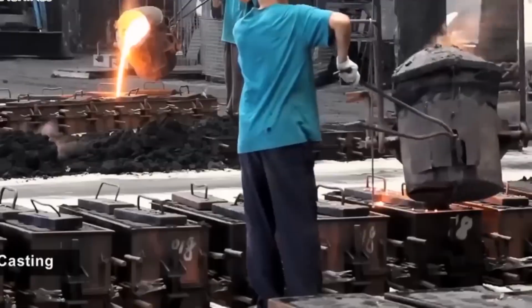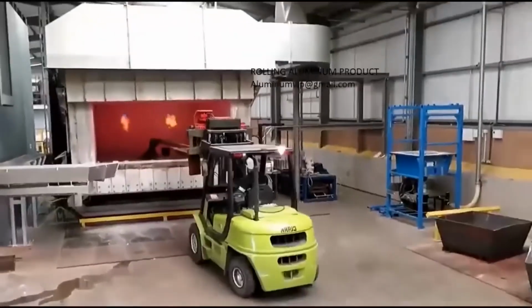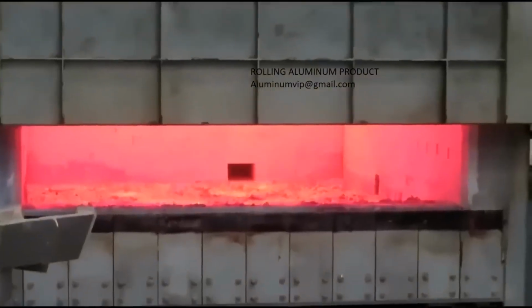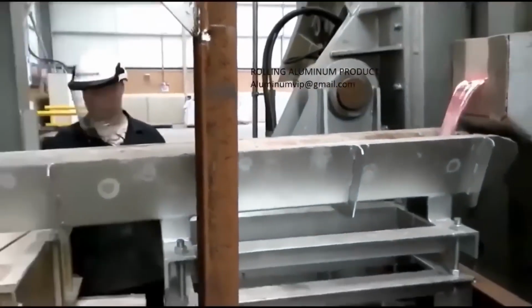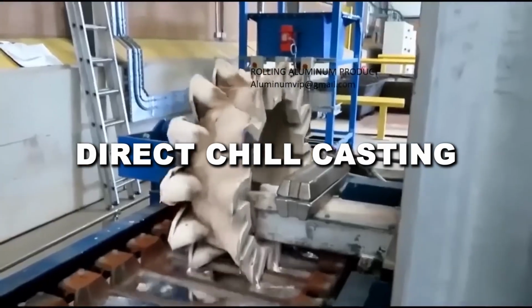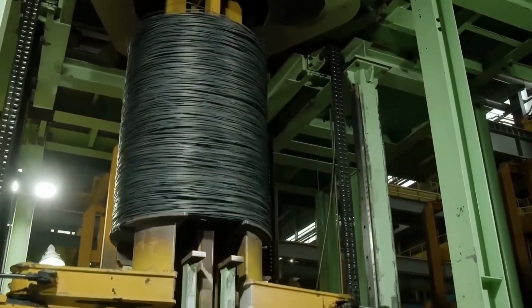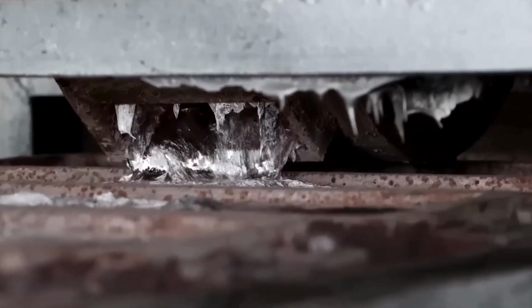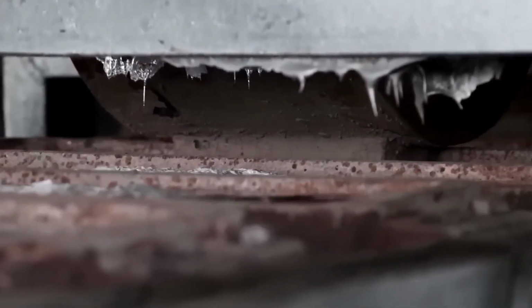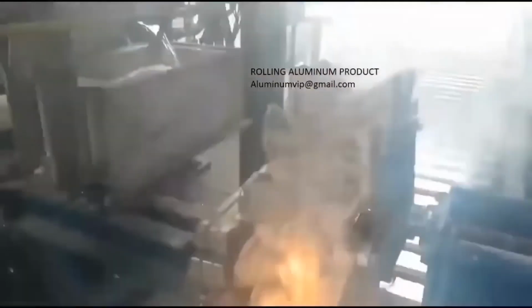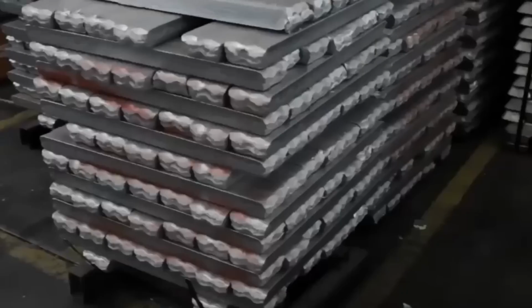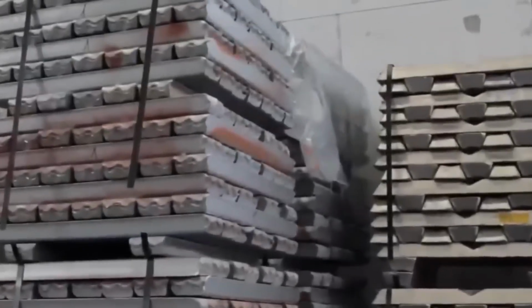The molten aluminum is carefully poured into massive molds where it begins to take on a solid shape. One of the most common methods used in aluminum recycling is direct chill casting. This technique involves continuously pouring molten aluminum into a mold while spraying it with water to rapidly cool the surface. The sudden temperature drop prevents cracks, warping, or weak spots, ensuring that each batch of aluminum is uniform and structurally sound. At the end of the process, what started as a pile of discarded soda cans has now become a set of massive, gleaming aluminum ingots.